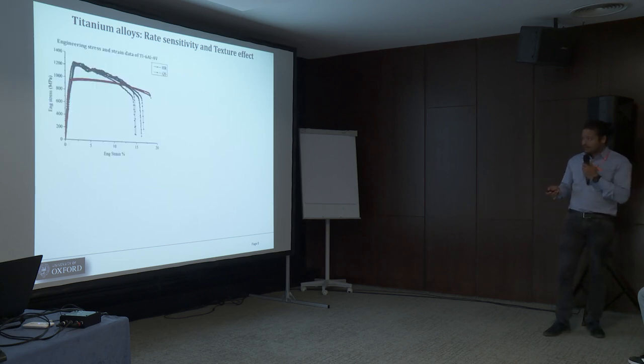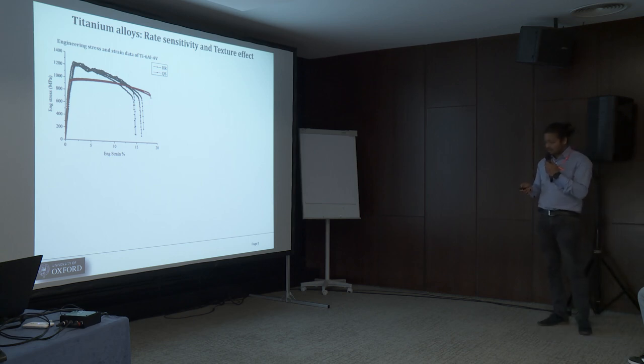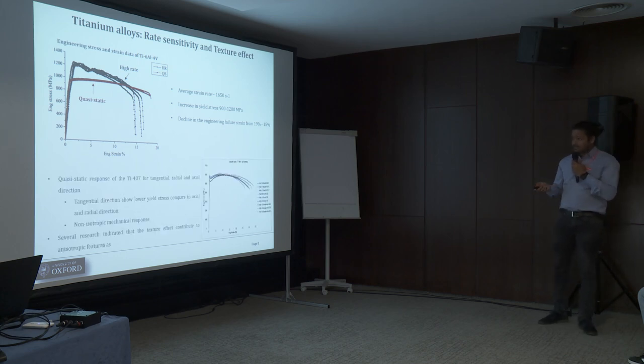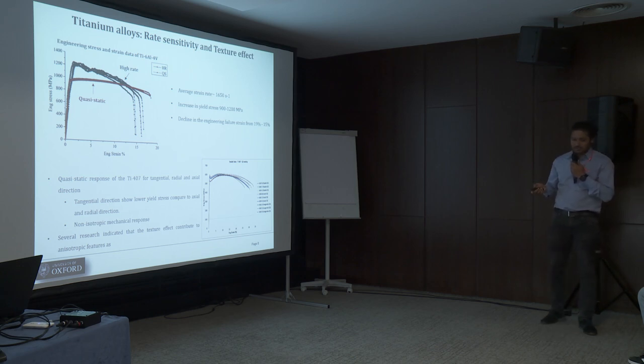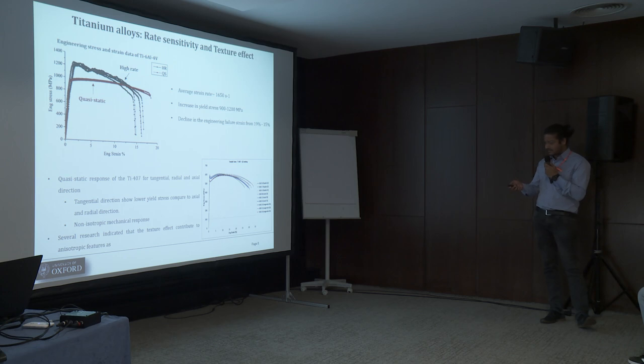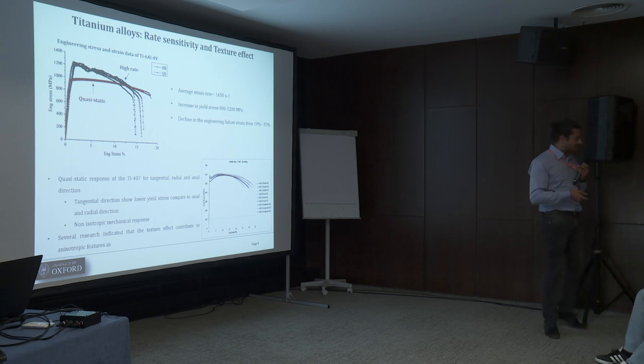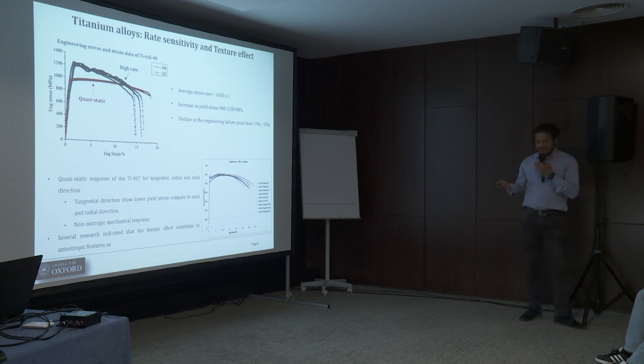As we know, titanium alloys are rate sensitive and texture dependent. The graph clearly shows that when we increase the loading rate, it does increase the yield strength, but at the same time reduces the engineering failure strain. Further, testing different textures — such as the quasi-static response of Ti-6Al-4V in tangential, radial, and axial directions — shows different yield strengths and failure strains, indicating that this alloy, whether from conventional or advanced manufacturing, might show some sort of anisotropy.